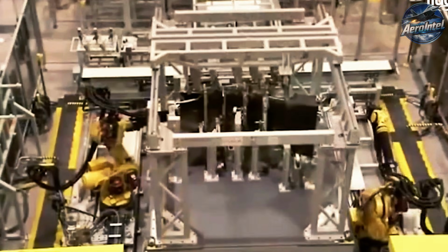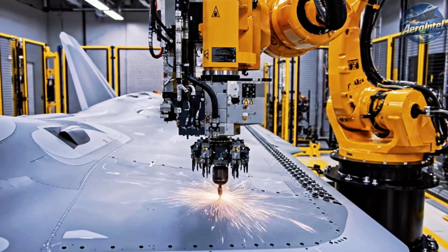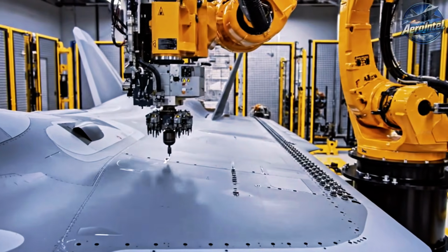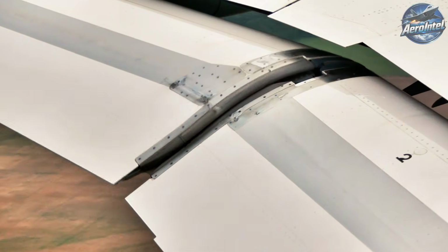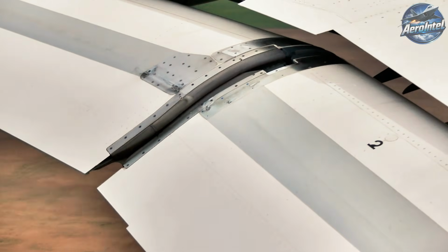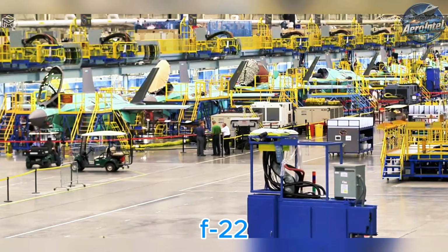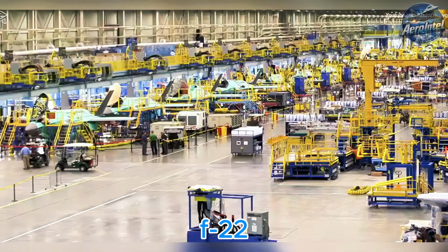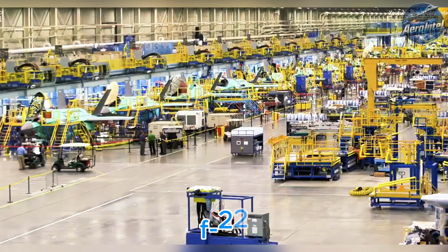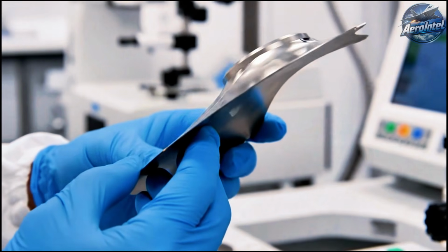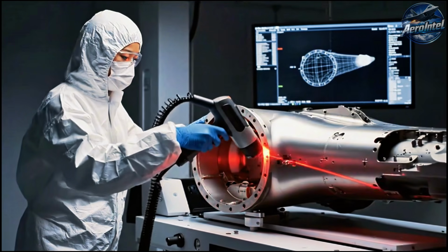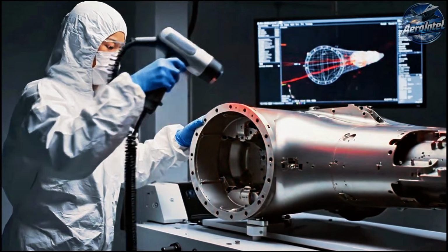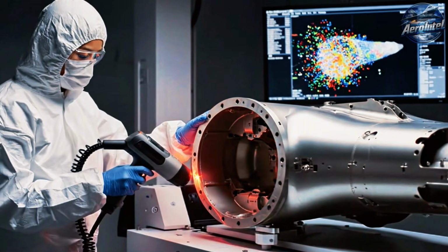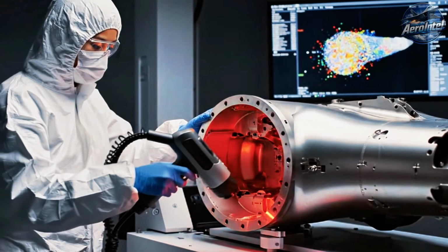Stealth aircraft are designed from the ground up to manage those returns, to redirect radar energy away from the source, rather than bouncing it back. The rivets on an F-22 are not just structural fasteners. They are flush rivets, machined to sit perfectly level with the surrounding skin, with tolerances measured in thousandths of an inch. The panel edges are aligned so precisely that the gap between adjacent panels is barely visible.